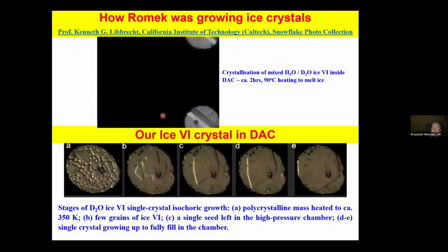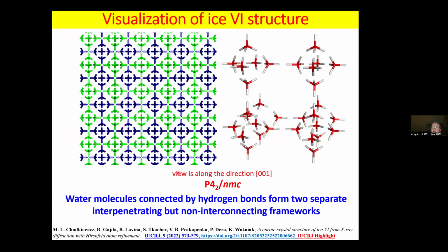And we also crystallize ice in a diamond anvil cell. This is crystallization of mixed H2O/D2O ice VI. And below is crystallization of D2O ice VI in a diamond anvil cell, different stages of this crystallization. And then we collected X-ray data at APS, and I can see Dongzhu among the participants of this webinar. And once again, thank you very much for excellent help and work with this data collection.